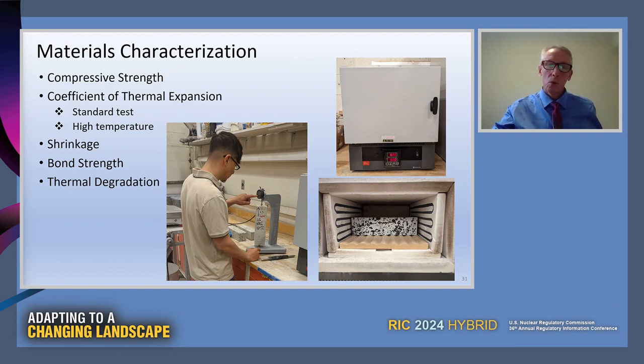So, doing some basic materials characterization like compressive strength, but really the big part of the research is postulating that there could be a high temperature event, a ruptured pipe of some sort, anything along those lines. So we're looking at how the concrete and the grout, and specifically that connection between modules, will perform under high temperatures. So in terms of the materials characterization, we're looking at coefficient of thermal expansion measurements and going up to about 600 degrees centigrade. And to do that, we're using the furnace and a measurement technique called digital image correlation. We're also looking at shrinkage, bond strength between the grout and the concrete, basically anything that would affect the integrity of that grouted joint. And then the last part of the project, we'll have some modeling for thermal degradation of the joint. Next slide, please.